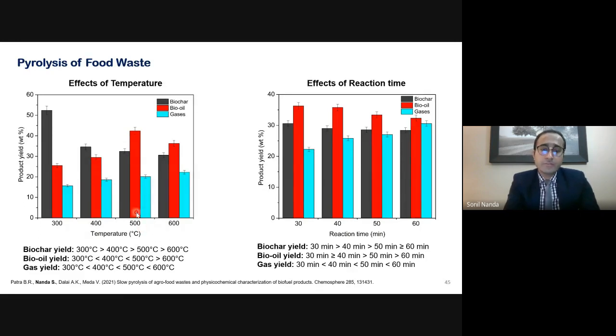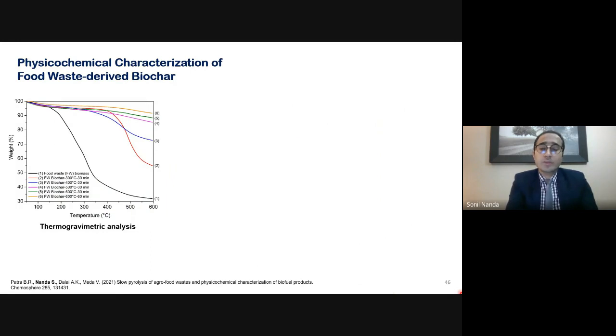So when we used food waste, we found that the bio oil yield was high at 500 degrees Celsius, because when we further increase the temperature, secondary reactions could come into play, and because of the secondary reactions, the bio oil yield is suppressed and the gas yields are enhanced. This shows that the gasification reactions within the pyrolysis are enhanced at high temperature and longer reaction times, because these are considered the secondary reactions. Now, coming to the thermogravimetric analysis of different biochar-based products which are obtained from the food waste.